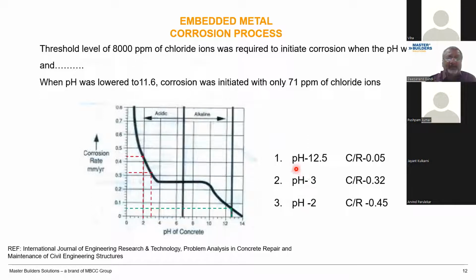Now, when the pH of concrete is in the alkaline zone, say 12.5, my corrosion rate is 0.05 millimeters per year. The same concrete, when the pH drops to 3, the corrosion rate goes to 0.32 millimeters per year. So my reinforcement bar is getting sacrificed. And with just one drop in level from 3 to 2, my corrosion rate shoots up to 0.45 millimeters per year.